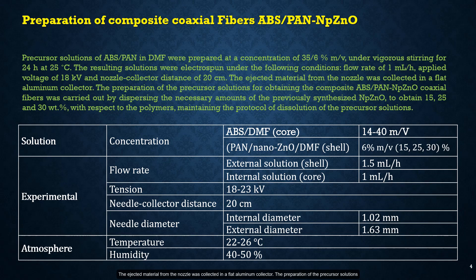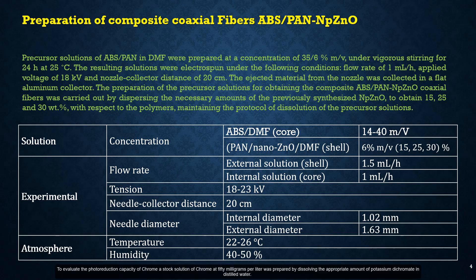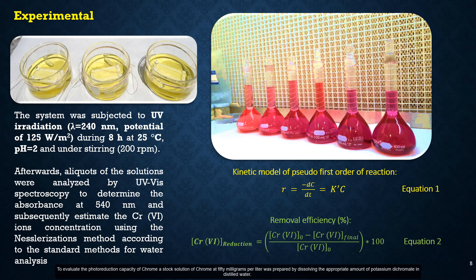The preparation of the precursor solution for obtaining the composite ABS polymer with zinc oxide nanoparticles coaxial fibers was carried out by dispersing the necessary amounts of the previously synthesized zinc oxide nanoparticles to obtain 15, 25, and 30% by weight with respect to the polymer, maintaining the protocol of dissolution of the precursor solutions.